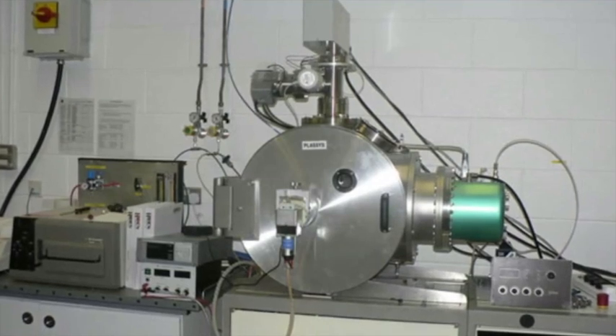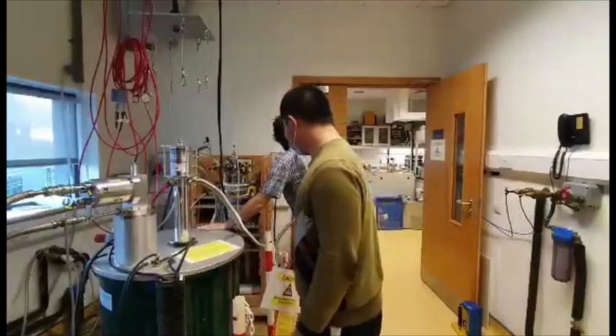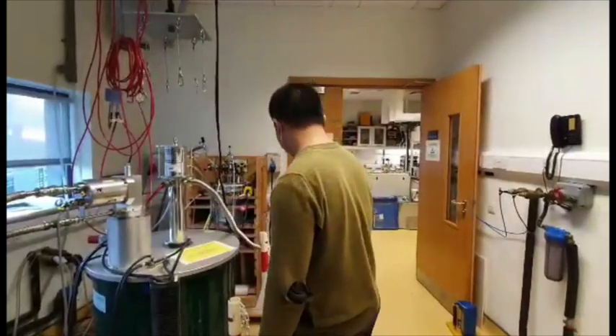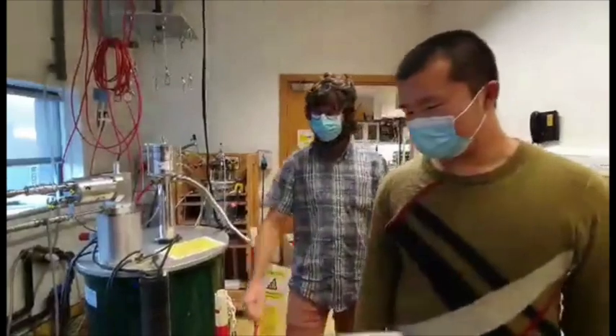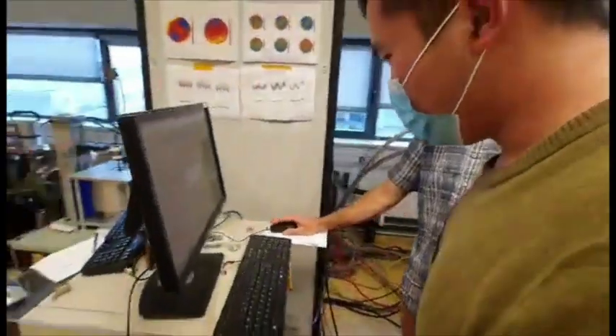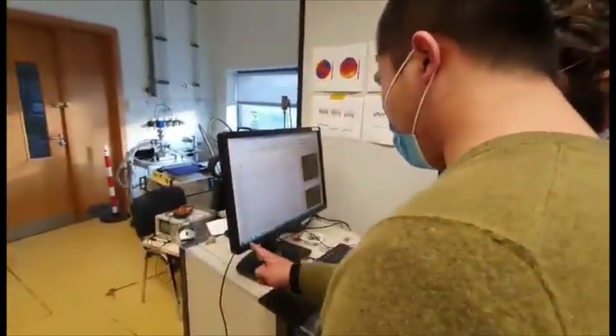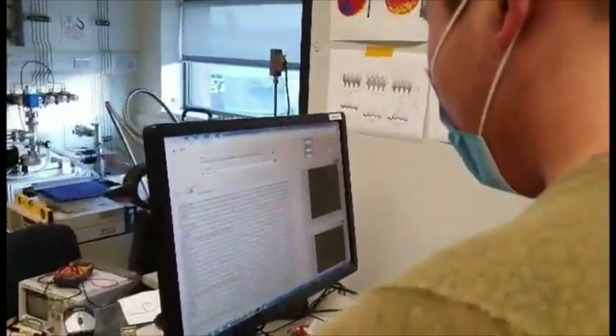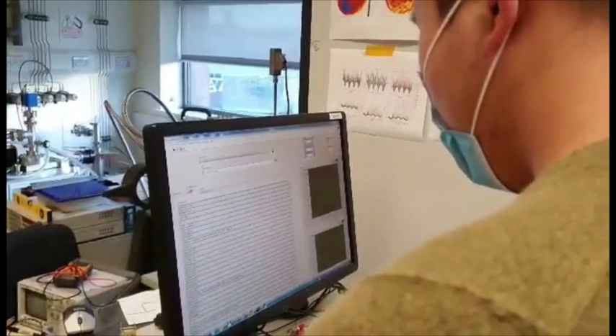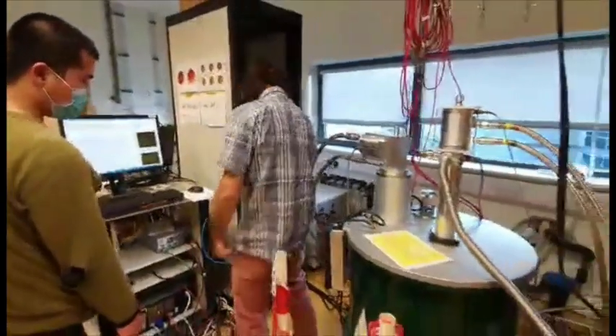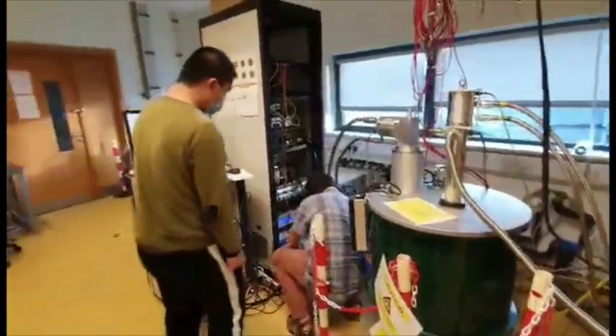Next, we pattern them lithographically into the shapes we need for detailed electrical measurements, which we make with different directions of field and current, and also different temperatures. Sometimes we need to see harmonic response to AC excitation. Here, Simone and Zhang are making measurements on a new 10 nanometer thick amorphous film of dysprosium cobalt at temperatures from 5 to 300 K in a magnetic field of up to 5 Tesla. It's produced in the bore of the big green superconducting magnet, where no liquid helium is needed.